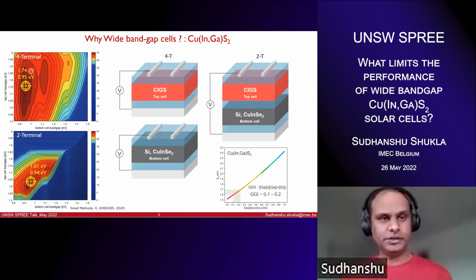So as you know, this is the color plot which tells you that if you choose a top cell material of a certain band gap, and you combine it with a certain bottom cell band gap, you get the maximum efficiency somewhere with a bottom cell band gap of about 0.95 to 1 eV, close to silicon that you use, and also CIGSe, for example.